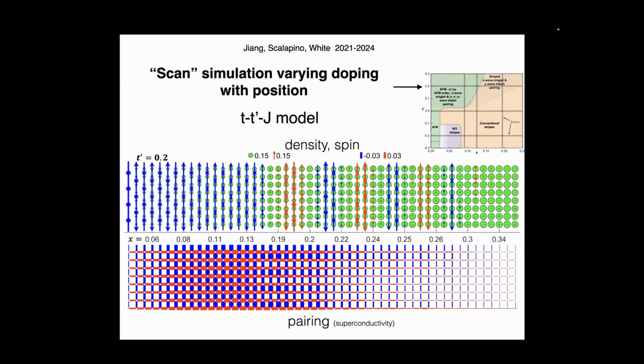It's well known experimentally that the cuprates have d-wave superconductivity. So this is a pairing operator, the expectation value of c dagger up, c dagger down on a bond, and it can be a horizontal or a vertical bond. It's between the same state, but because they mix particle numbers, you can get something that's non-zero. So it's a direct measure of a BCS type of order parameter. The color difference shows the sign, and the red-blue pattern means it's a d-wave superconductor here. There's always a question of how strong it is, what your units are, and that's a little bit tricky. But you can at least see relatively that in this low-doped region, it is a nice d-wave superconductor on the electron side, and it doesn't really go away for a long time.